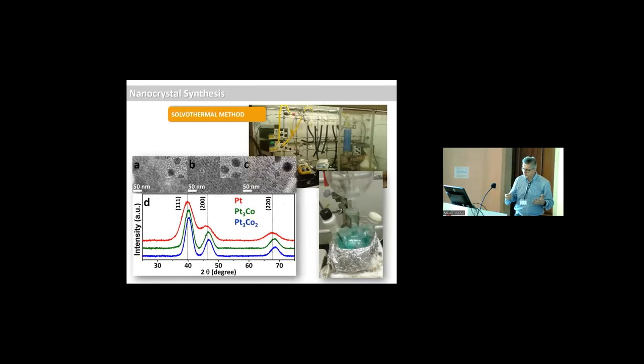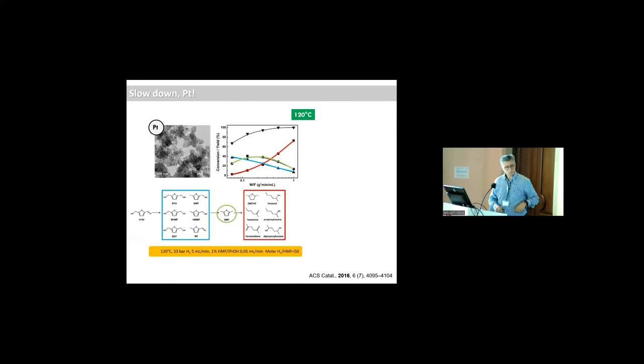So we just decided to make bimetallic nanocrystals, and we focused our attention on cobalt. Why cobalt? Because it's not active for hydrogenation. And so we make platinum rich in cobalt, so platinum 3, cobalt 2, and platinum with less cobalt. So what is the situation with the standard catalyst, platinum on carbon?